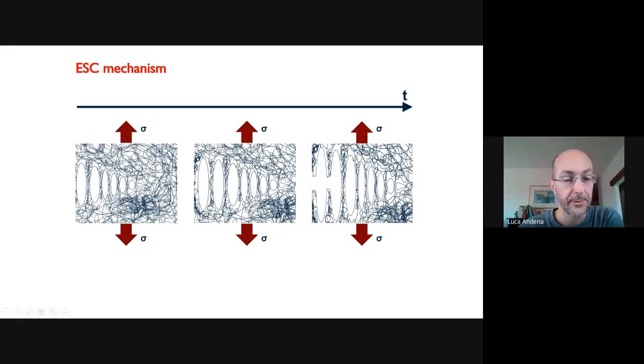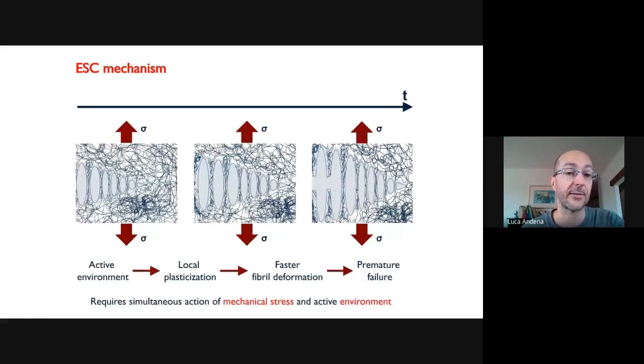Typically, when we observe failure in polymeric materials, we observe the formation of a craze, which is the structure generating from an already present defect within the material. The craze starts to grow with the formation of some voids with this fibrillar structure in which the material is drawn from the bulk and the fibers are stretched up to the point in which they break. In presence of the active environment, the environment can diffuse within the craze and locally cause a plasticization of the macromolecules of the material. And this plasticization, which occurs because of the affinity between the agent and the material, basically makes it much easier for the fibers to deform and eventually break, thus reducing the mechanical strength of the material.